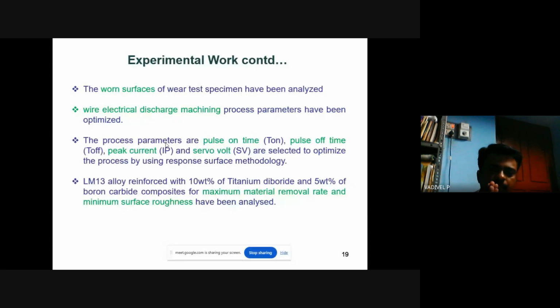The LM13 aluminum alloy reinforced with 10 weight percentage of titanium diboride and 5 weight percentage of boron carbide composites have been analyzed for the maximum metal removal rate and the minimum surface roughness. So we have chosen the weight percentages of 10 and 5. These are the maximum weight percentages of these ceramics. This is used for analysis of MRR and minimum surface roughness.